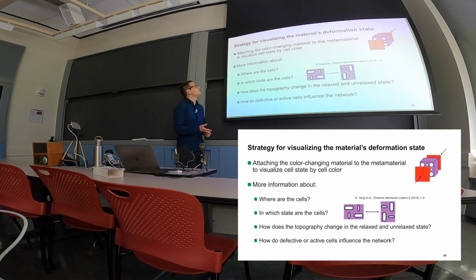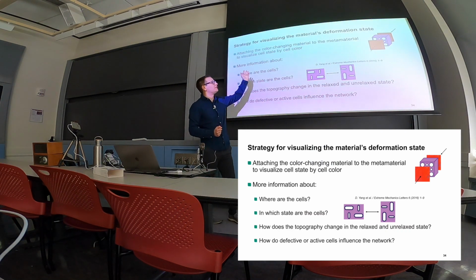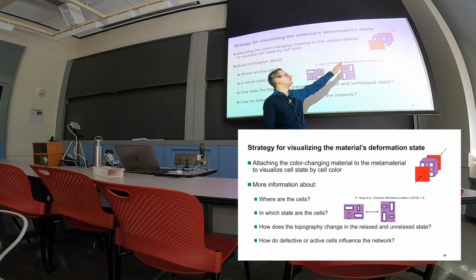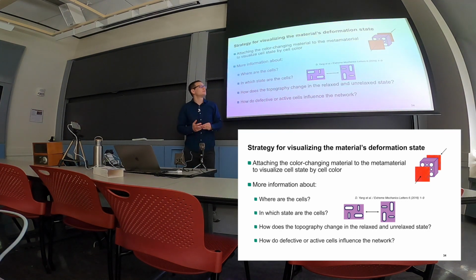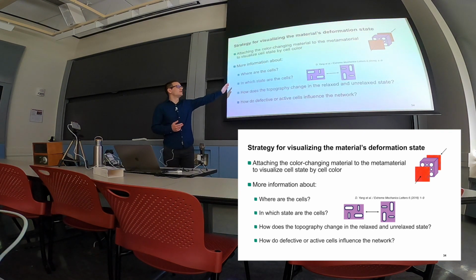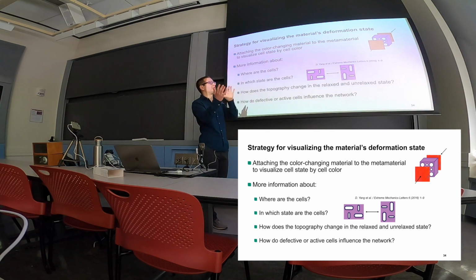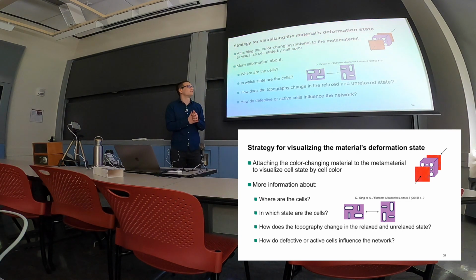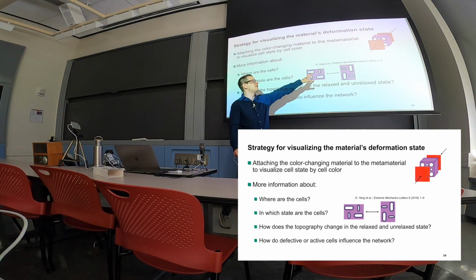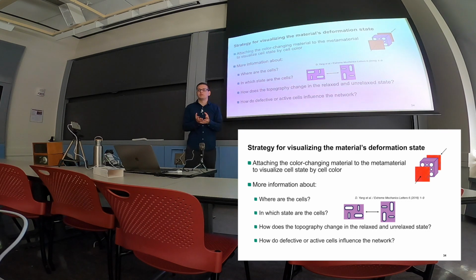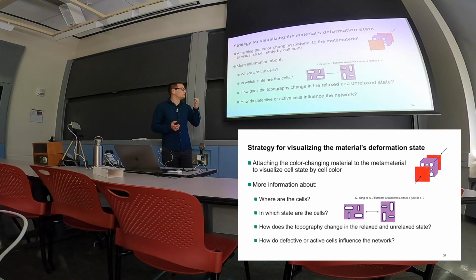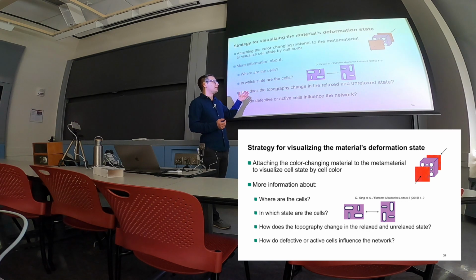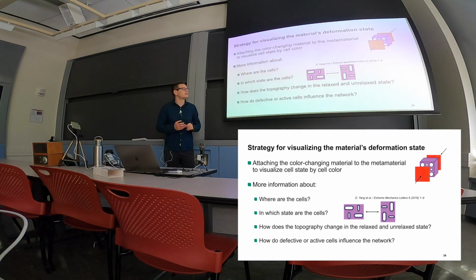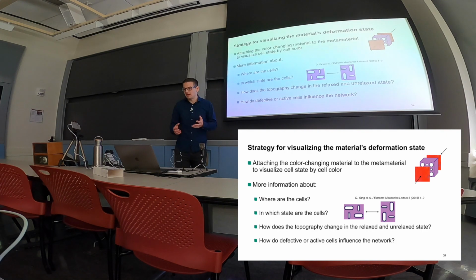And now my goal in the thesis over here was that I wanted to attach this color-changing material as a front and back layer to this multi-bistable network to see whether I could gain more information about this network. First of all, knowing where those cells are, which is more difficult to sense if there's a black or a backing layer and the top layer out of the same material. And I also wanted to see in which state those cells are, so whether they are currently laying or standing, which is difficult if we don't know the edge conditions of this whole die. And I also wanted to know how the topography changed in the relaxed and unrelaxed state, and how active or defect cells inside of such a network influence the overall behavior of that network.